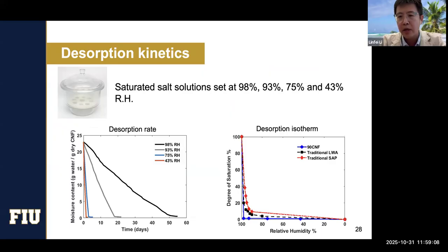We are comparing the cellulose nanofiber we're using with traditional lightweight aggregates as well as traditional SAP. As you can see, the good thing is that the cellulose nanofiber can release more water in terms of degree of saturation compared to the lightweight aggregate as well as SAP at high relative humidity. I think this creates a huge potential. Even as your system starts hydrating and the relative humidity goes down, while it's still at a high level, like 97% or 95%, the CNFs are very sensitive and will start releasing water to the system. But lightweight aggregates or SAP may not respond immediately, or have a slower response.